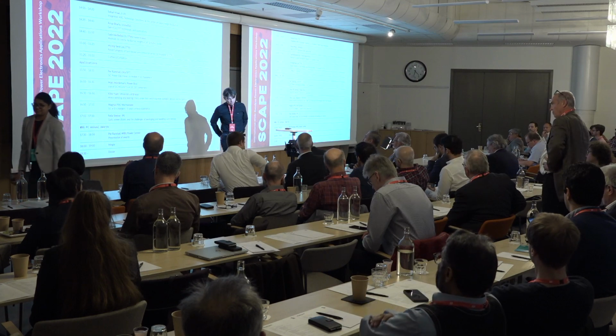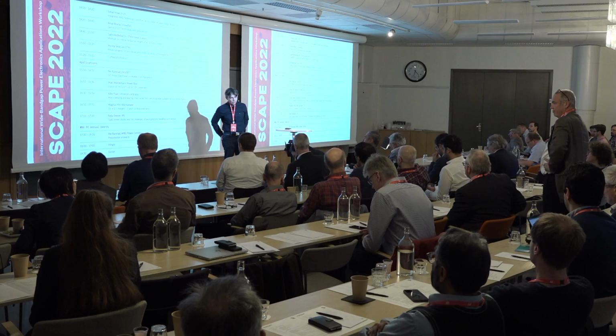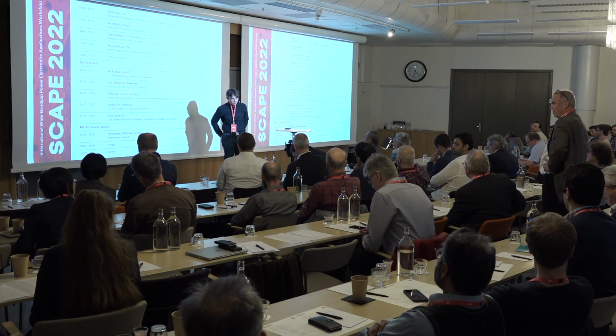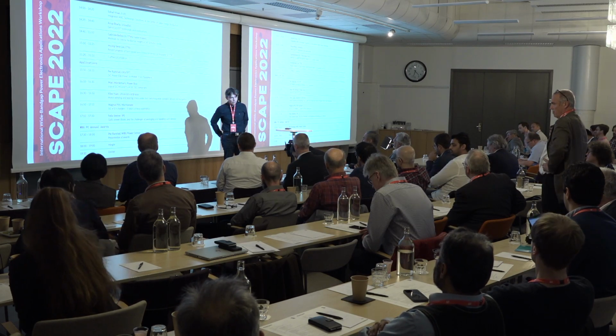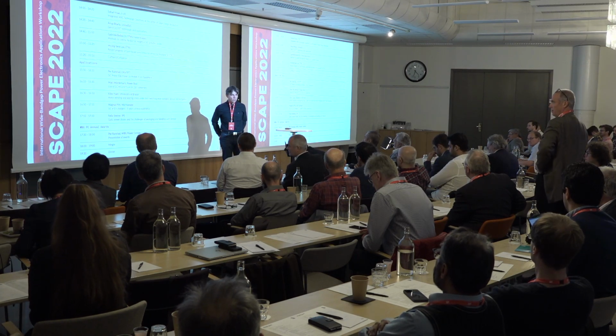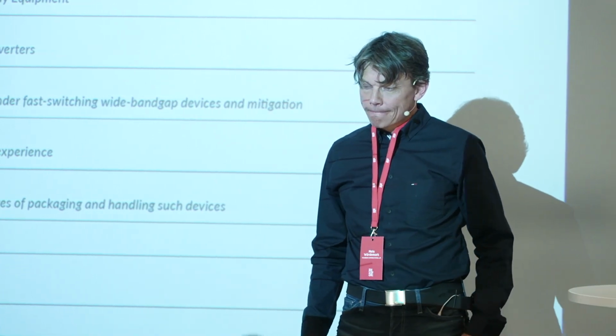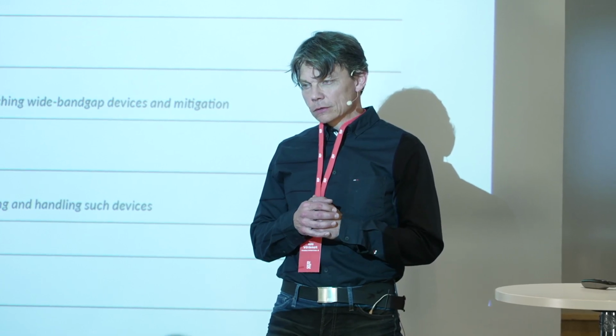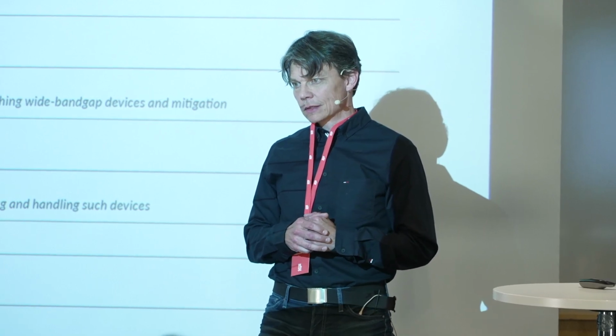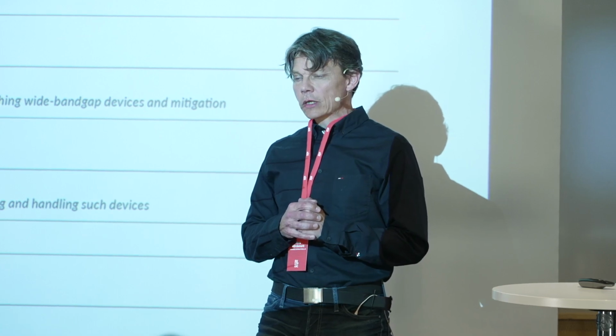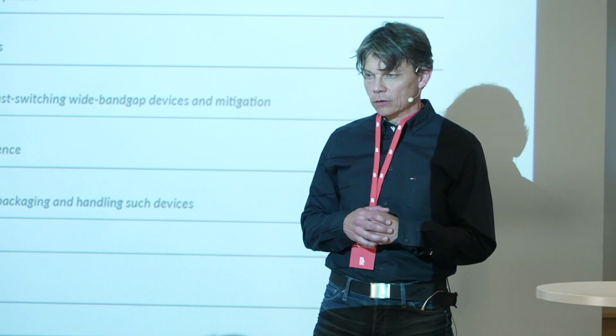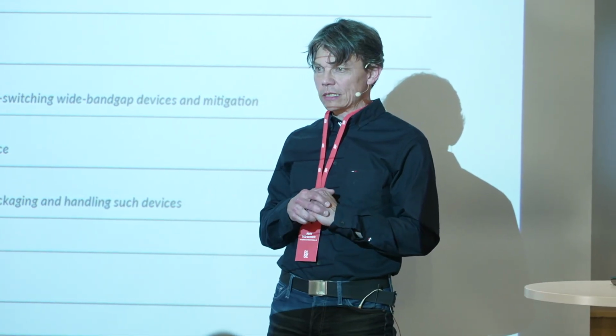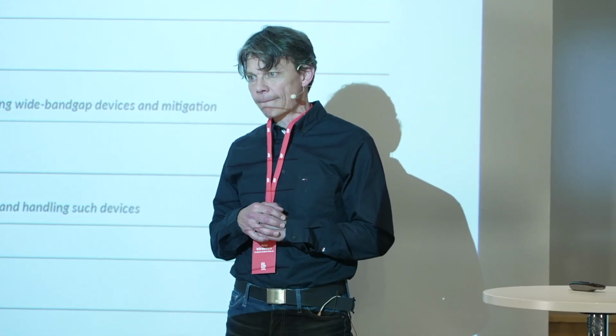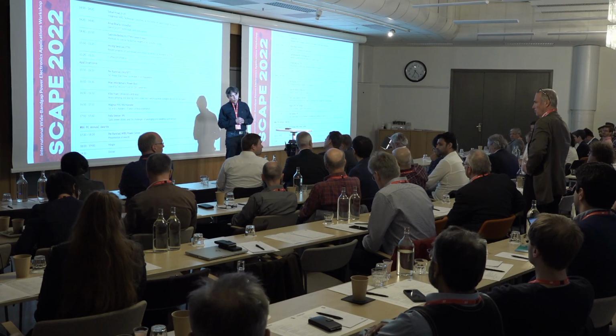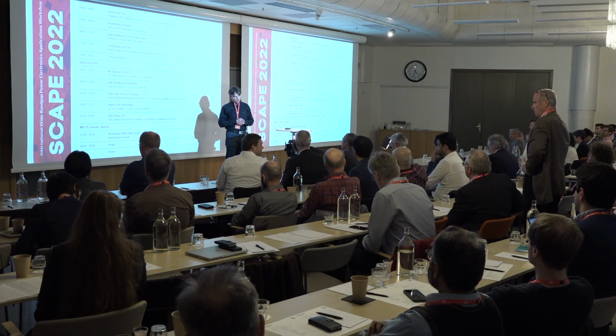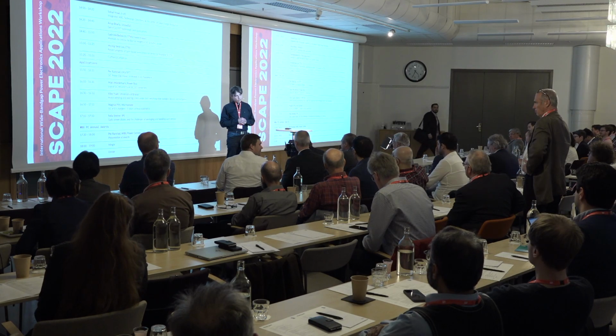In slide 10, you have compared a 200 volt with a 650 volt device, and then you reached the conclusion that for some applications you're not going to switch to SiC. Could you explain why you have compared these two devices? Haven't you found silicon carbide with a lower breakdown voltage? No, we haven't found that. We found the available 650 volt. We know that they are quite good, but you can't replace a 200 volt silicon MOSFET with them. We're looking for silicon MOSFETs in that range with low RDS-on. Maybe we can use silicon carbide, but our investigation shows that it will not work well. Due to that there are so many GaN devices in that voltage range, don't you think it's more suitable to switch to GaN for that application? Yeah, I think so. Yes. Good. Thank you.